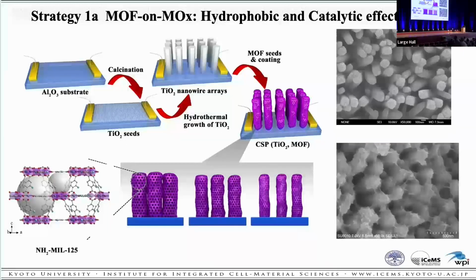We have designed and fabricated a hybrid system to create a semiconductor with a large surface area, and MOFs with specific entrapping and enrichment effects on the target molecules, and synergistic functions at the interface between these two materials. The diagram shows the preparation of the titanium oxide MOF core-shell structure. Firstly, we pyrolyze a layer of titanium oxide seed crystal around 10 nanometers on the aluminum oxide substrate on the prefabricated electrode. Then hydrothermally grow the titanium oxide nanoarray, and after calcination and cleaning, directly put it into a master solution of MOF for MOF cladding growth, and realize the regulation of MOF shell layer component thickness through parameter control.